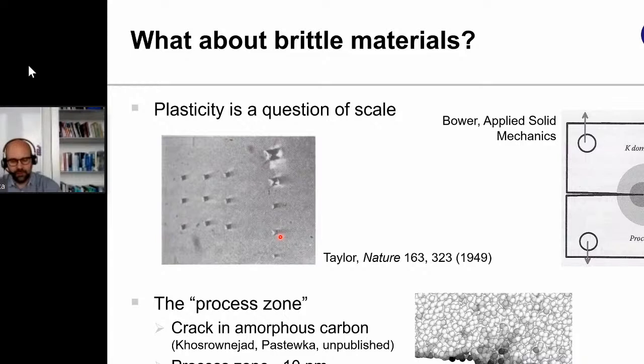And if you look into fracture mechanics, of course, the stress near a crack tip becomes very large, and in most materials there is a region that's often called the process zone, in which something happens that is not elastic deformation, but plastic deformation. So at small scales, even in cracks of brittle materials, you will have plastic deformation. One system that we're currently looking at is amorphous carbon, which has a process zone on the order of 10 nanometers. For all metals and most ductile materials, the process zone is too large to be able to simulate it in molecular dynamics calculations. So maybe amorphous carbon is one of the few systems that has a process zone where some plasticity happens.